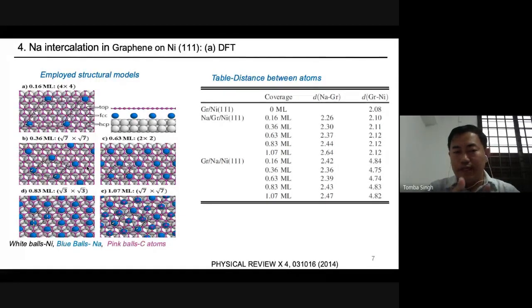Now we know that interaction depends on the distance. So to have a better idea about the interaction, let's see the distance between the graphene and the intercalated atom, and between the intercalated sodium atom and the substrate. There is also a high chance that the sodium atom may sit above the graphene instead of intercalating below it. So let's discuss that distance also from the DFT calculations. In the pristine graphene-nickel system, the distance between the graphene and the nickel is around 2.0 angstrom.